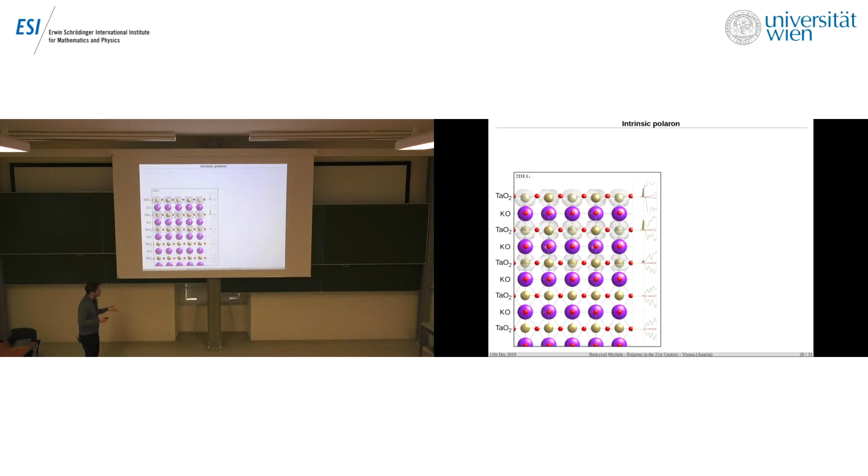Here is what could happen. This half of electron per unit cell actually forms a two-dimensional electron gas. You see, it's pretty much delocalized, and it goes up to the third layer, kind of. Then these layers are already bulk-like, where this state doesn't appear so much.